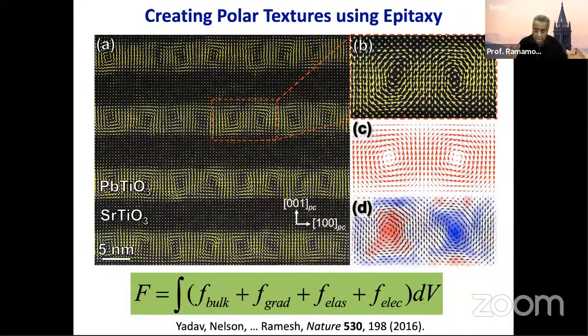And this is a textbook kind of a picture. What it is, is a superlattice of lead titanate, which is this layer, and strontium titanate. And the student who did the electron microscopy, this is an atomic resolution microscopy image. And these yellow arrows you see there are vector mapping of the displacement of the titanium ion with respect to the lead ion. And when we saw this picture, we said, oh my God, this is fantastic. And what we're looking at are vortex-like structures. One of them is rotating clockwise. The other one is rotating counterclockwise.